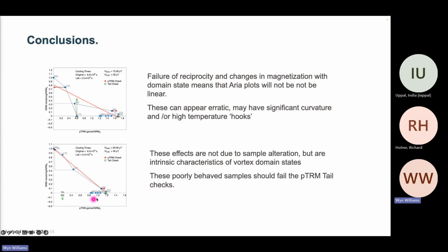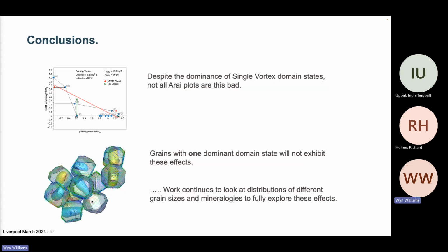One of the strongest indications, I think, of things going awry is these PTRM tail checks. Rather than PTRM checks, which you can fake, you can have samples that behave, but nevertheless give a negative PTRM check. PTRM tails are much more difficult to overcome. So PTRM tails, I think, are a good indication that something is not right in the magnetic domain states.